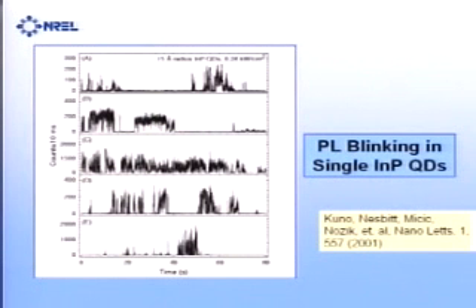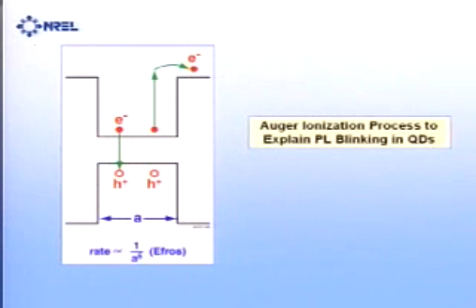And there's some history as to how I came upon this idea. It has to do with the blinking that occurs in single quantum dots when you look at the PL from a single dot, which the explanation was developed by Efros and had to do with the Auger ionization, because when this process occurs, this electron being out here produces a charge in the core which quenches the luminescence, and when it comes back, it turns it back on. That's the explanation for blinking. So it became apparent to me, well, if you could do this, you should do the inverse, which is to have a high-energy photon create 2 electron-hole pairs.